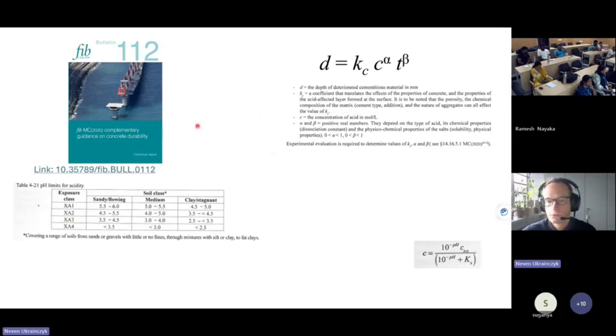So how to then predict? There is a very simple model. It's based on the square root model, because if you have here beta is 0.5, you basically have a square root, which is the fundamental moving boundary diffusion equation solution. But you also have the concentration here as an empirical parameter on the alpha. And alpha actually depends on the type of acid, because you have different types of acid.